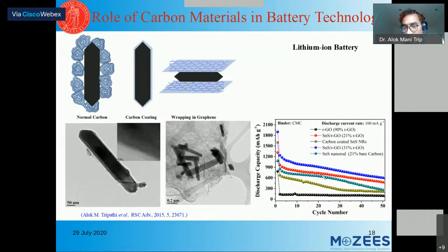With normal carbon, you see the trend is decreasing. With the carbon coated system, it's also losing. But when graphene was used, with just the type of carbon changed and everything else the same, it stabilized, and we are getting around 900 milliamp hours per gram, which is 4 or 5 times higher than normal graphite. This way we can select the material and the components of the electrode, and then we can increase the amount of charge stored inside the battery.